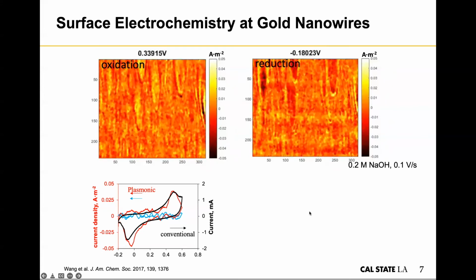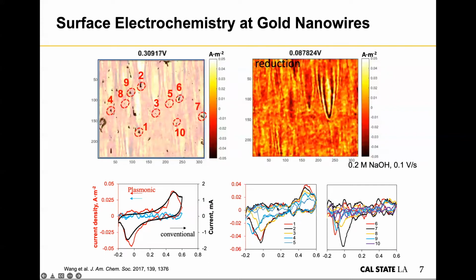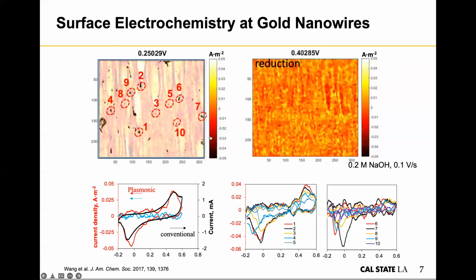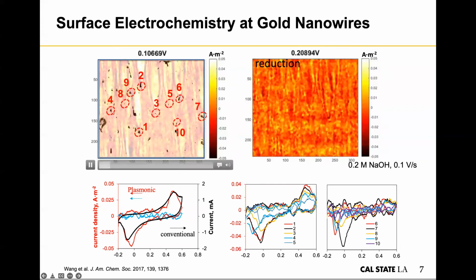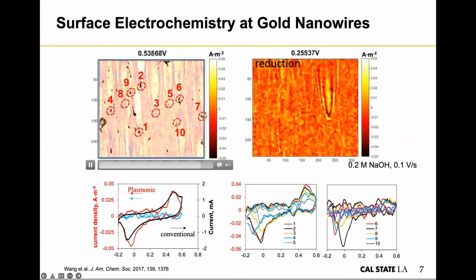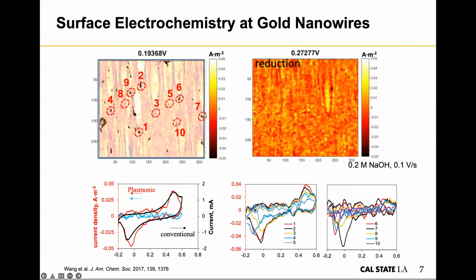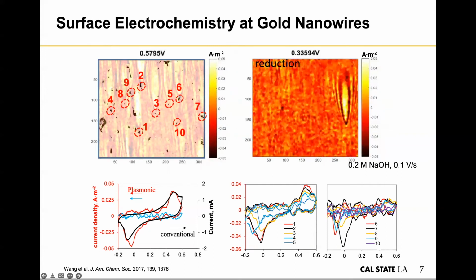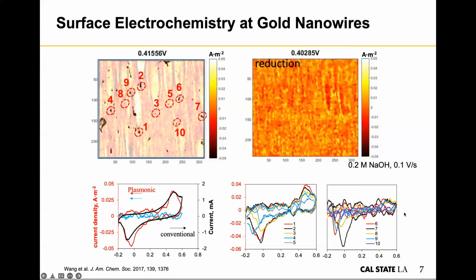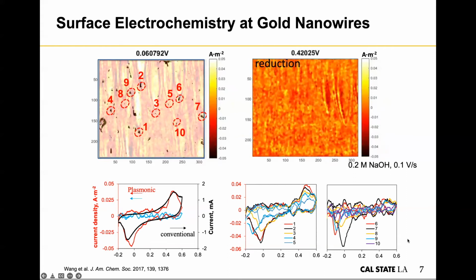And then we can extract information from different nanowires. So for example, we take 10 of them here, and from the optical image, you can estimate the size of the particles. And then from the PECM, you extract the current signal. And you can see that different particles give you different intensity and slightly drift in the potentials.